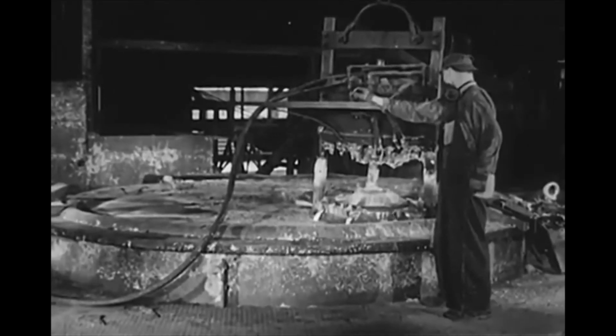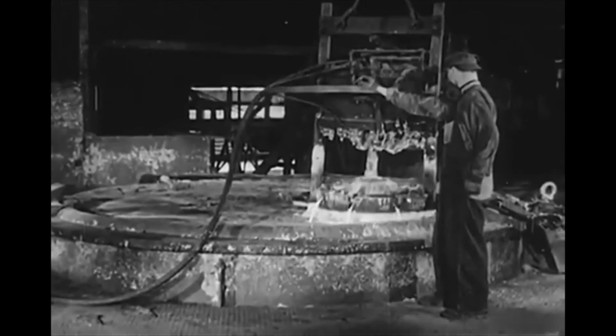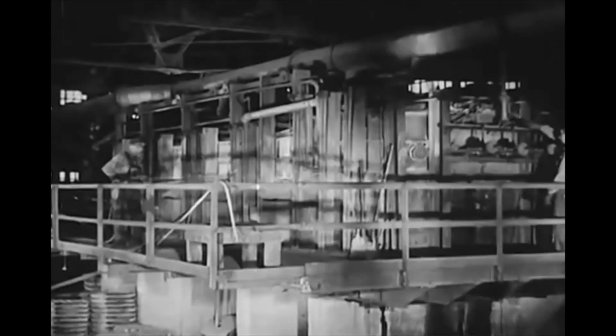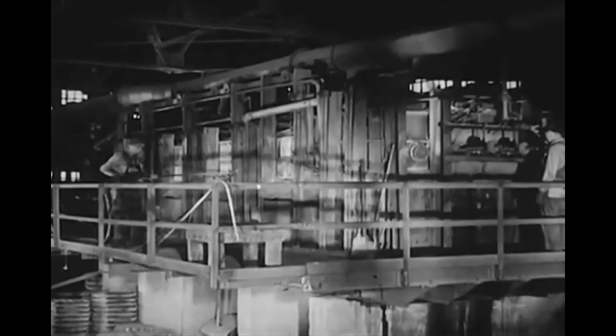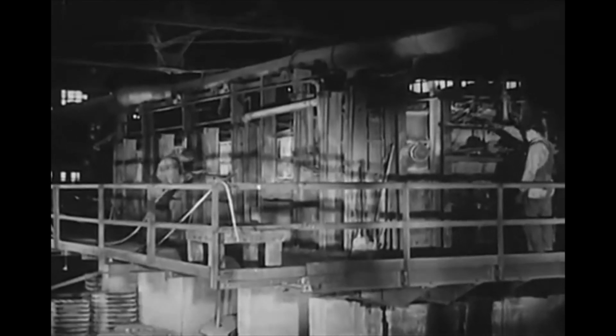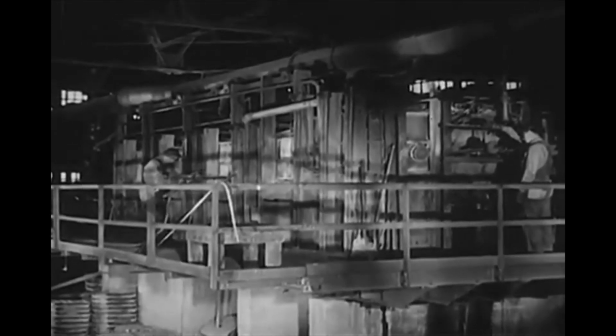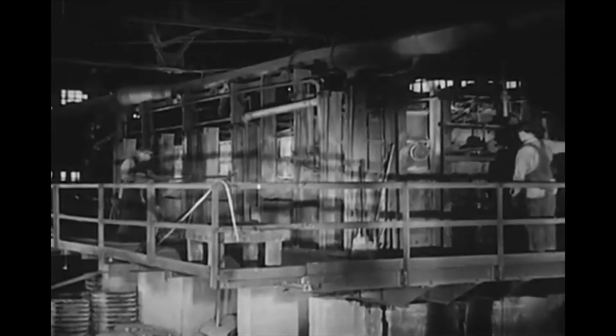This beautiful seal of the great state of Missouri is made entirely of silver recovered from refining Missouri lead. Designed by the distinguished American sculptor Paul Manship, it has been donated to the battleship Missouri. The zinc also removes whatever copper and nickel are left in the lead. After removal of the silver, the lead is pumped into a gas-fired furnace for removal of the 0.6% of zinc which has been left in the course of the desilvering process.